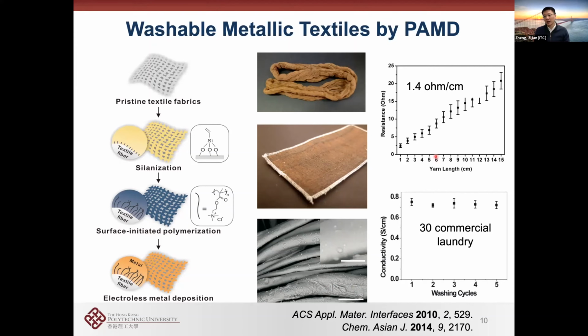And the key thing is that the conductivity is great, the resistance is really, really low, and the adhesion is great. We can go through commercial laundry, so you can wash in a laundry machine for 40 minutes at 40 degrees Celsius with detergents and dry it. That's one cycle, and then wash many, many cycles, no problem.